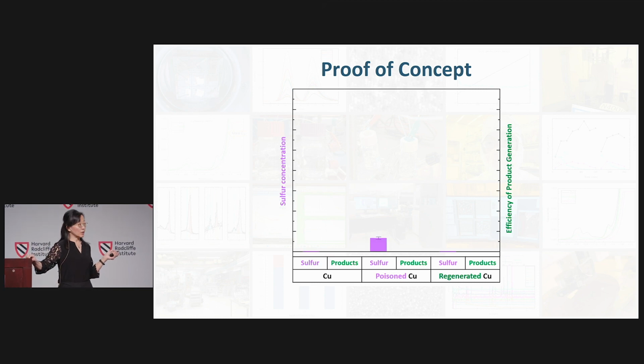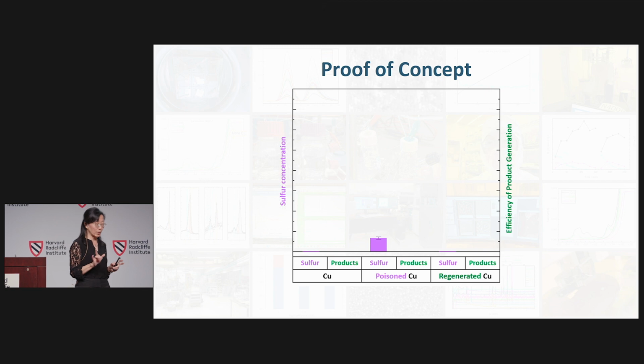The clean copper surface has no sulfur, so I forced a line at 0 there, a very faint purple line here. We use a model compound to introduce sulfur, actually we use 4 different model compounds, I'm showing you one here, to introduce sulfur to the surface, and we can quantify its concentration and the chemical environment. After we treat the surface with atomic layer processes, we reduce the sulfur concentration down to the detection limit of our instrument. The reason why I mentioned the detection limit is important, because I'm going to come back to that point in just a second. Okay, so we know what happened to the sulfur in our processes. Let's now look at how that affects the products that we produce.